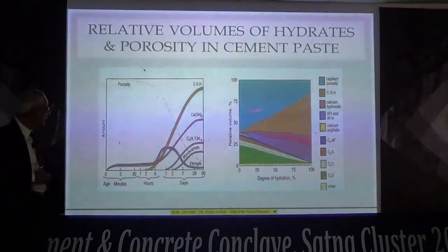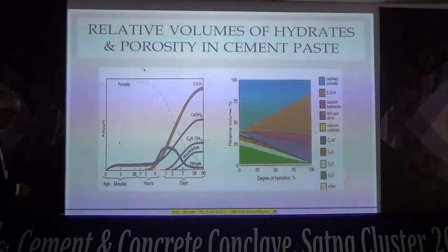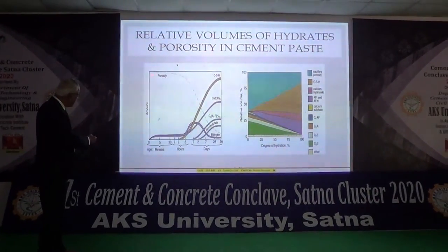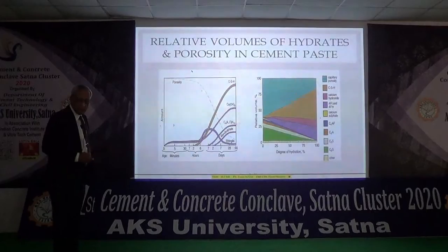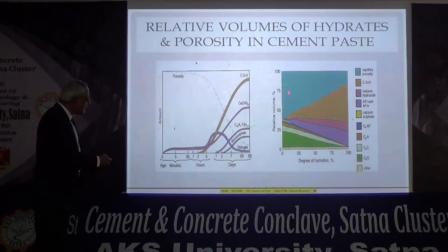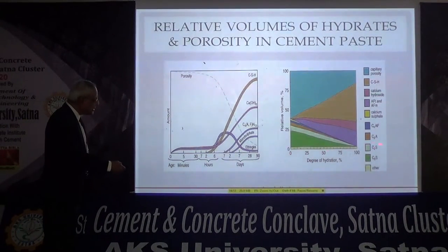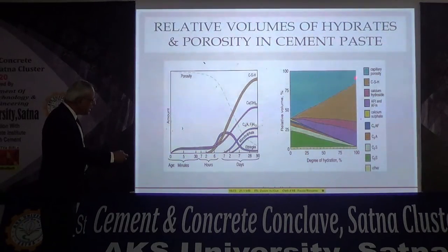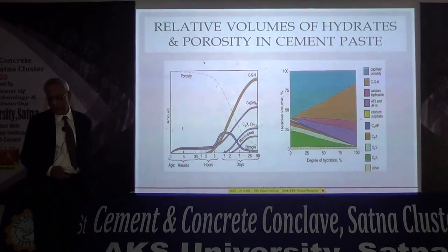The center one. What happens is that with time, which could be minutes, hours, and days, if you look at that, then what happens? Over a period of time, many of these hydrated phases grow in volume, and correspondingly the porosity keeps on coming down. Ultimately, what is very important is that this blue portion is almost 100% hydration that you have already tracked, and you find that even with 100%, you are left with a very large proportion of capillary porosity.